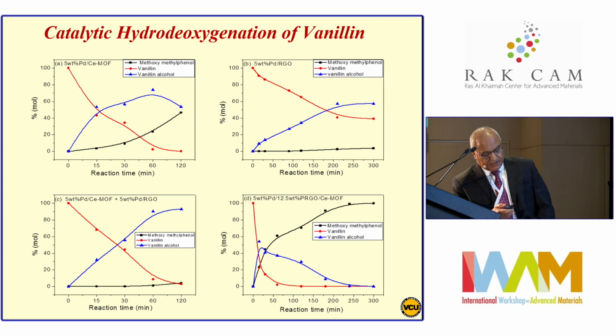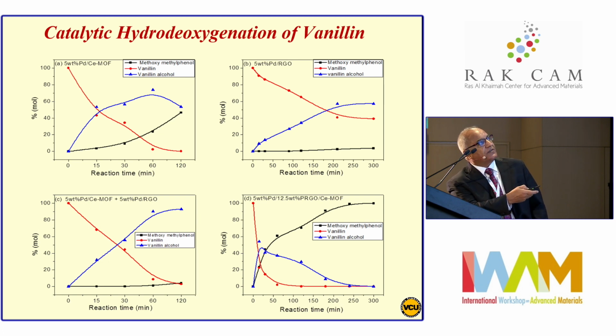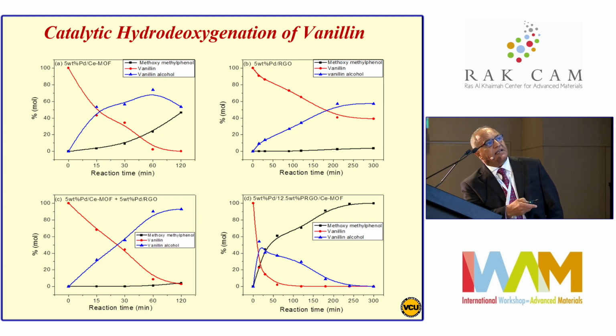To look at the reaction activity, what we're seeing is the conversion of vanillin, which is in red here, as a function of time. The vanillin goes down. Remember, we have two products. One is the undesirable product, vanillin alcohol, which is the blue. The desirable product is the methoxyphenol, which is the black. If you use only palladium on cerium-MOF, with no graphene hybrid structure, we see that most of the product actually goes to the vanillin alcohol, which is the undesirable product, and very little goes to methoxyphenol. If we use graphene oxide as a support with the same amount of palladium catalyst, you see even less of the methoxyphenol, and again the major product for the conversion of vanillin is vanillin alcohol.